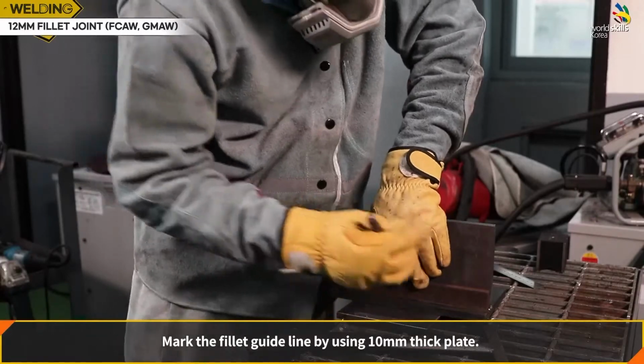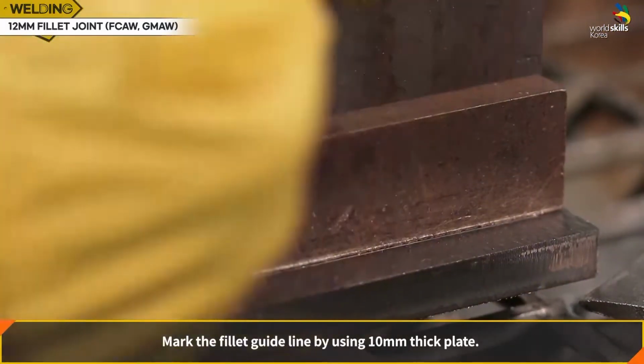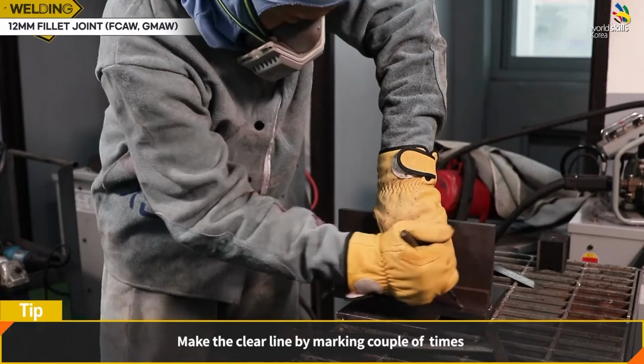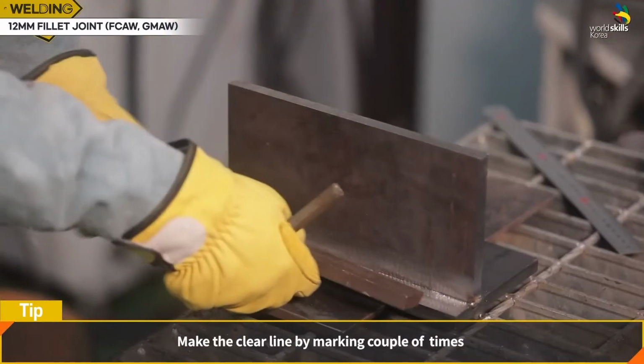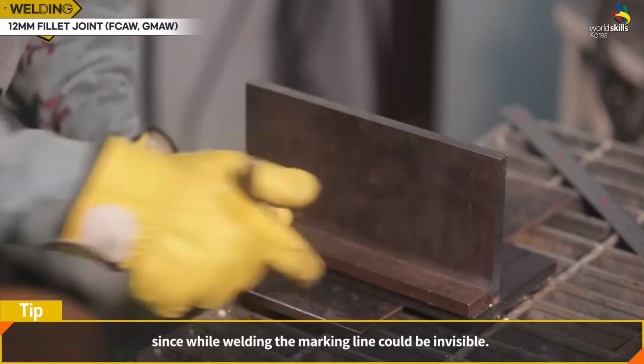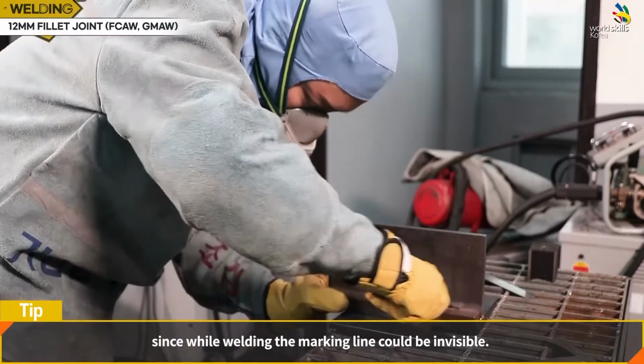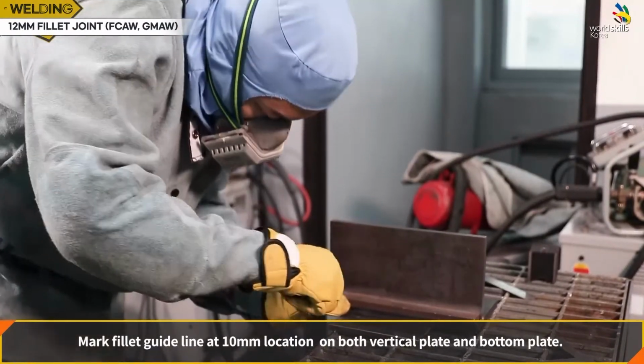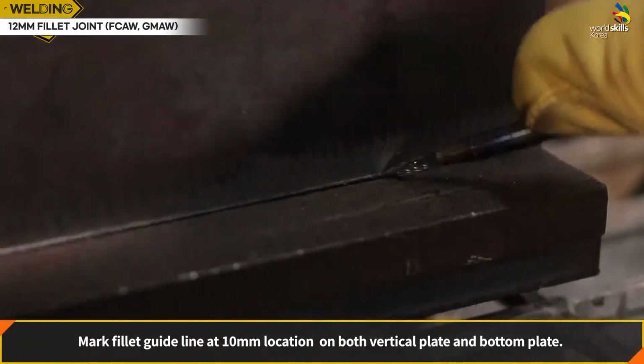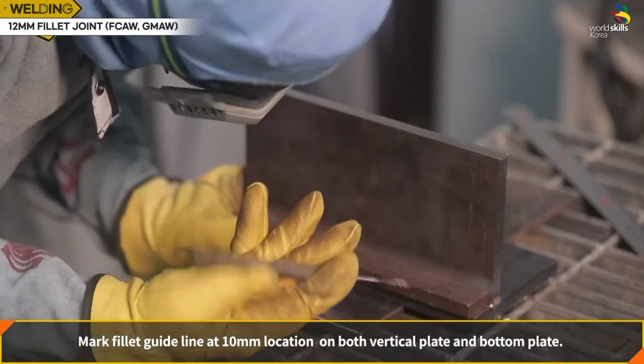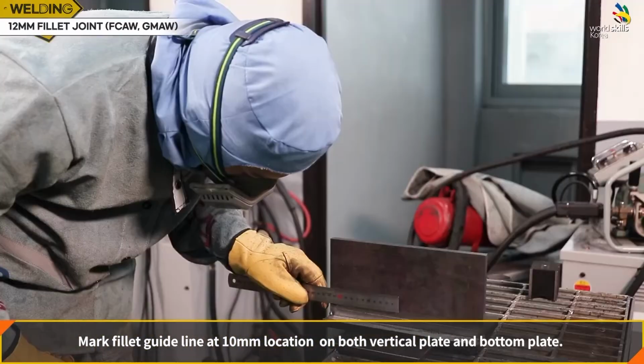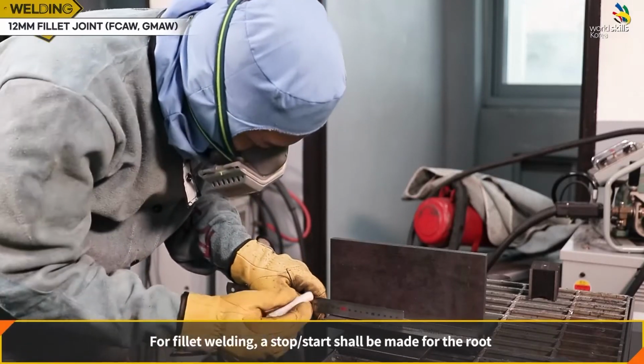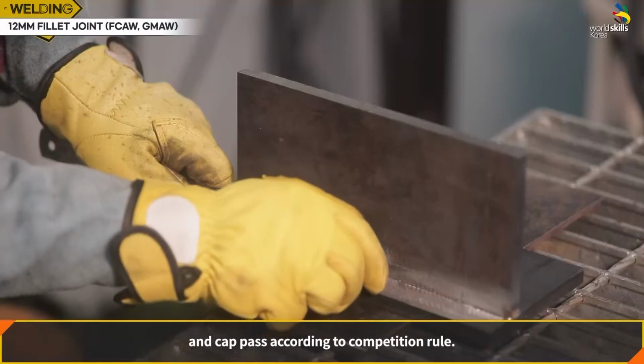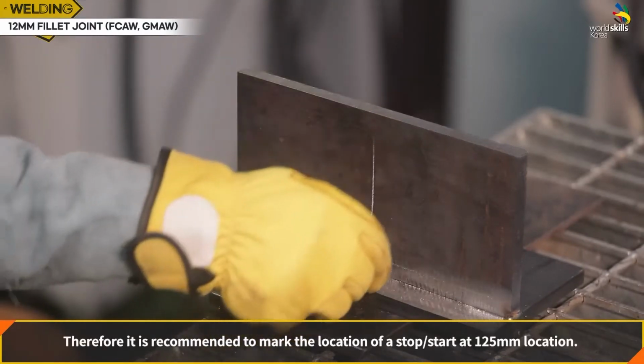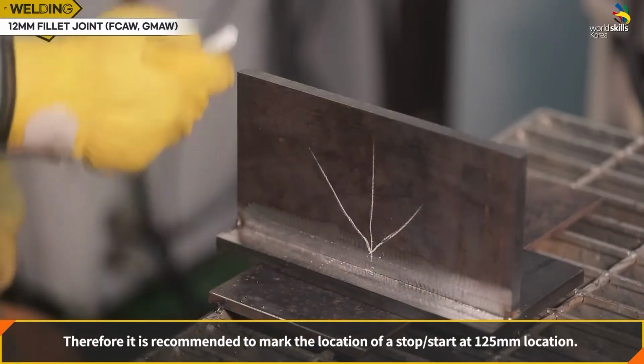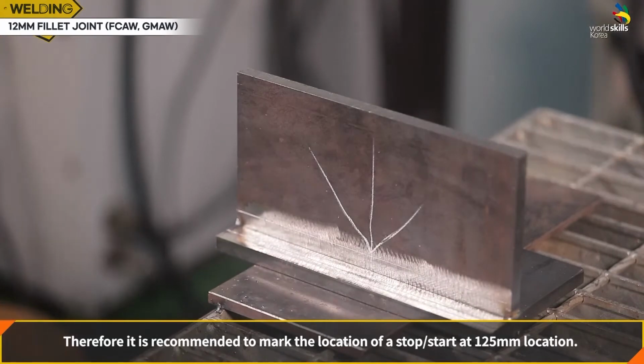Mark the fillet guideline by using a 10 millimeter thick plate. Make the line clear by marking a couple of times, since the marking line could become invisible while welding. Mark the fillet guideline at the 10 millimeter location on both the vertical plate and bottom plate. For fillet welding, a stop-start shall be made for the root and cap pass according to competition rules. Therefore, it is recommended to mark the location of a stop-start at the 125 millimeter location.